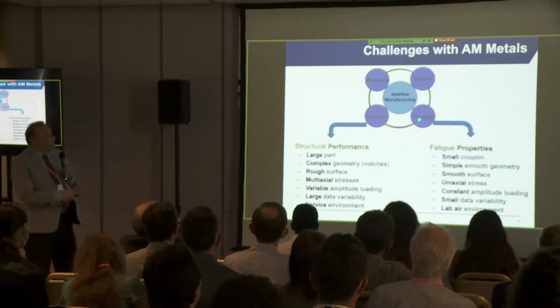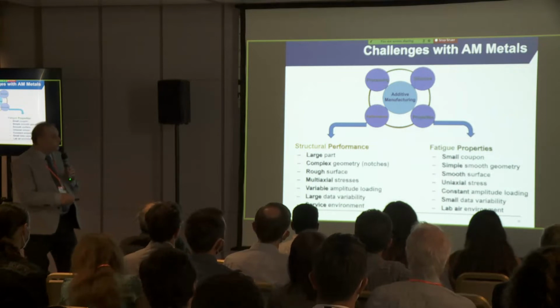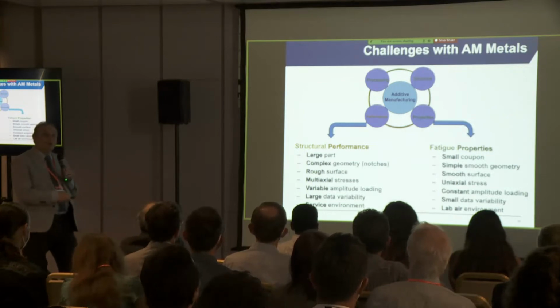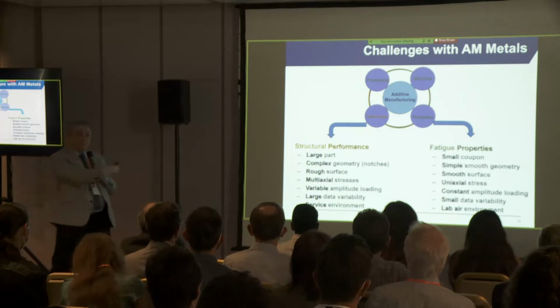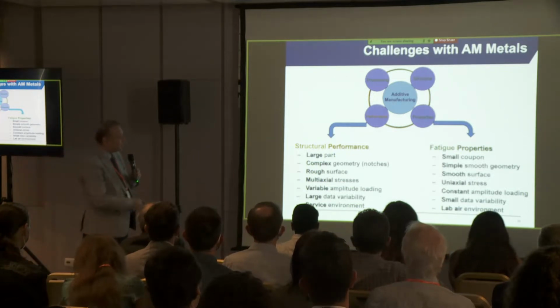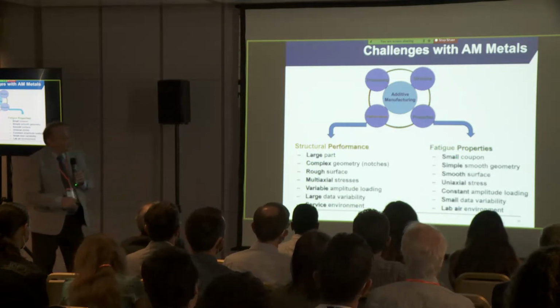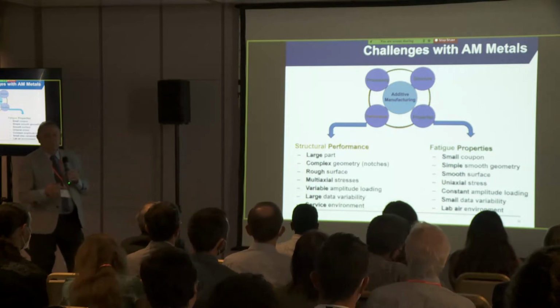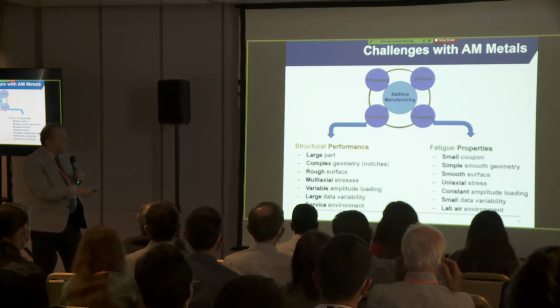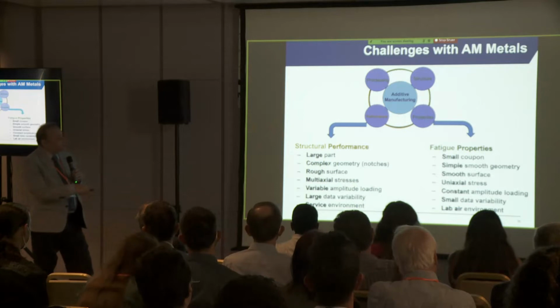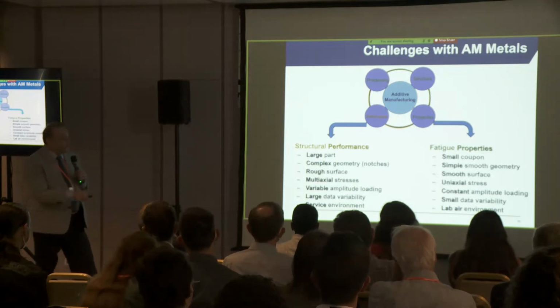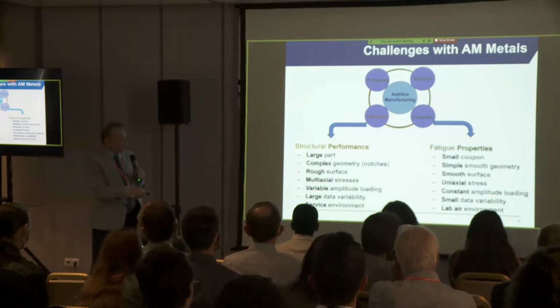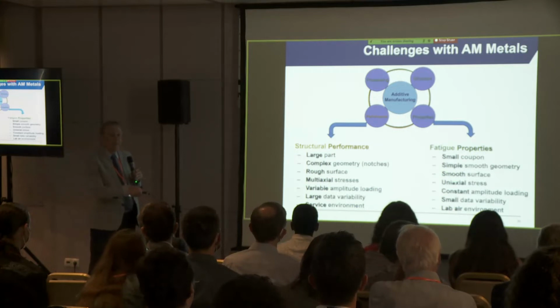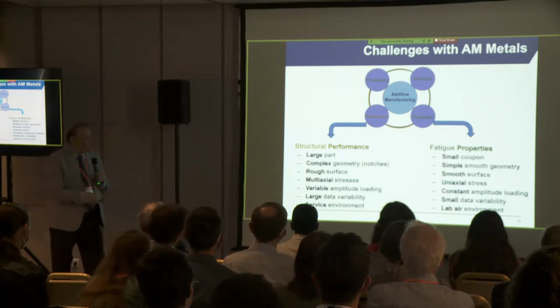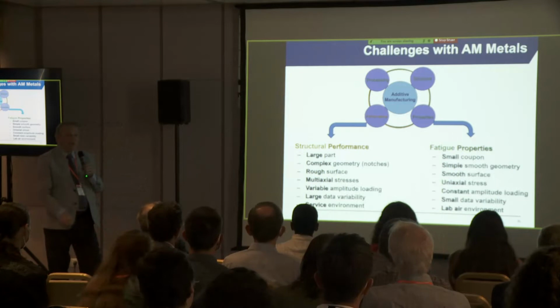So when we are generating properties on a specimen, we typically deal with small coupon specimens. In actual components, we have larger parts. In view of the variability I talked about earlier, that's an important issue. When we talk about properties, we usually use smooth specimens. In a part, we usually have a complex geometry that has notches. In coupon specimens, we deal with a smooth surface. In additive manufacturing, we have a rough surface.